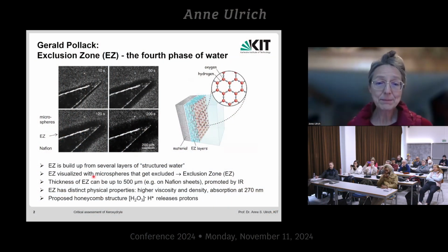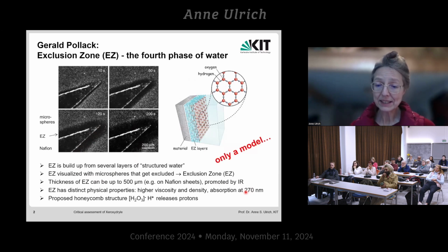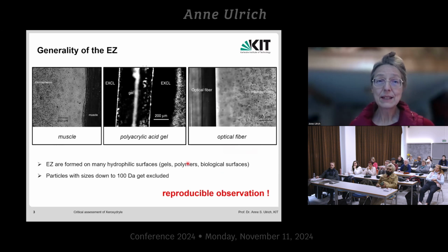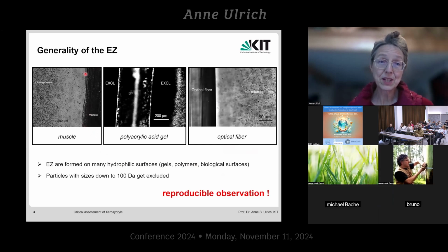But the concept is that this water in the so-called exclusion zone has certain properties, and they are, for example, characterized by a fingerprint of UV-vis absorbance of 270, 280 nanometers. And it would be curious to find out more about this. That is the classical view, asking, is it possible to extract it or somehow scrape it off the surface? And in fact, this exclusion zone is very general. It has been observed, and we have reproduced that in our lab here on the surface of numerous materials. Here you see a muscle fiber forming an exclusion zone. Here a polyacrylic acid gel forms a nice exclusion zone. Even an optical glass fiber forms an exclusion zone.